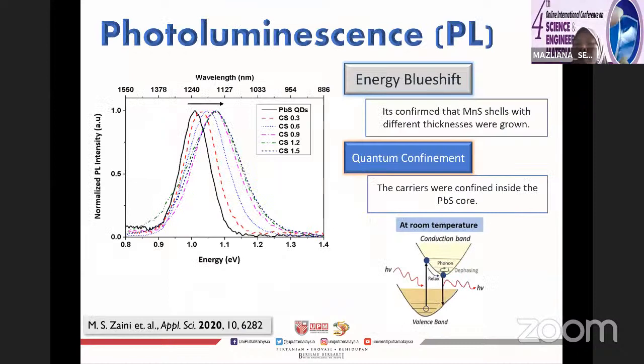After that, we ran PL. This is the photoluminescence measured at room temperature, for different shell thicknesses, where we grow the shell from 0.3 up to 1.5 monolayers. When we run the PL, we can see a blue shift, which confirms the formation of the MnS shell, because the presence of the shell increases the confinement of the carrier.